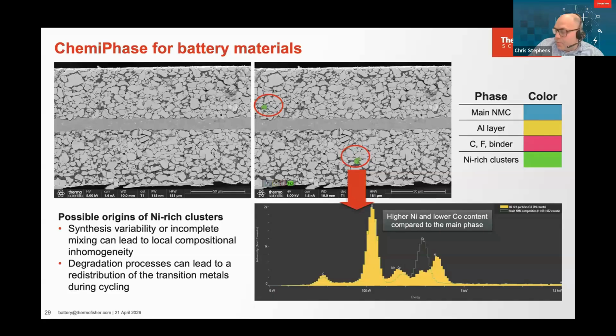In this case, it's a nickel-rich cluster, and this local inhomogeneity isn't really obvious from looking at the SEM image alone. So the system is able to really identify features in the chemistry that you would not see from the image. What we would say is these are the sorts of things that would accelerate the degradation of the material.